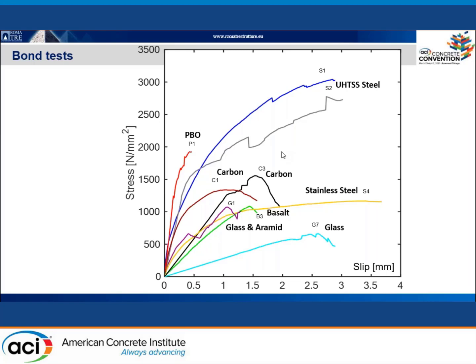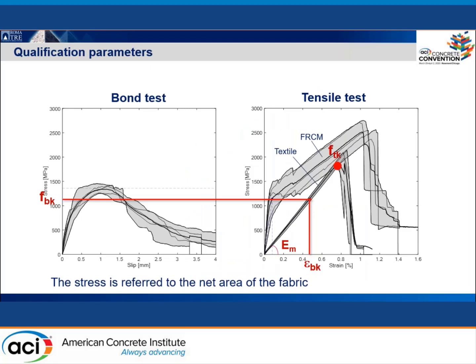Such different behavior when you make a bond test on this system suggests that the European guideline make use of both tests, bond and tensile test, because from the bond test you may be able to have the capacity in terms of strength, while from the tensile test you can have an estimate of a sort of equivalent modulus of elasticity and a design strain that you can consider for real application.